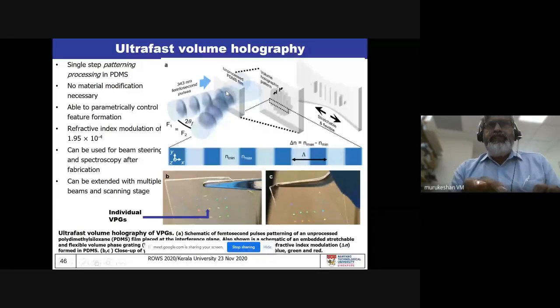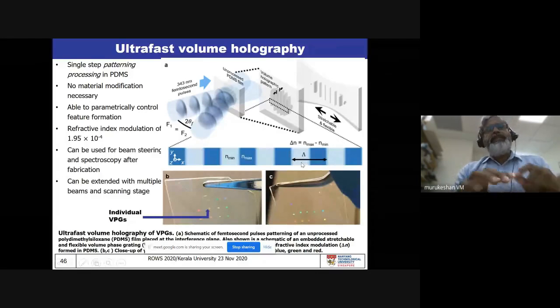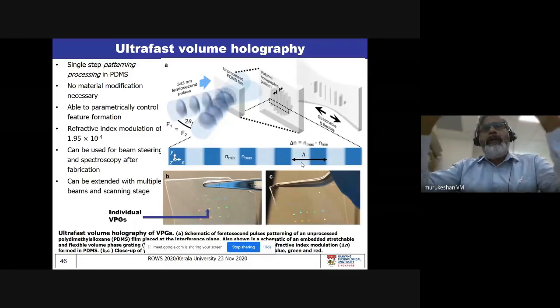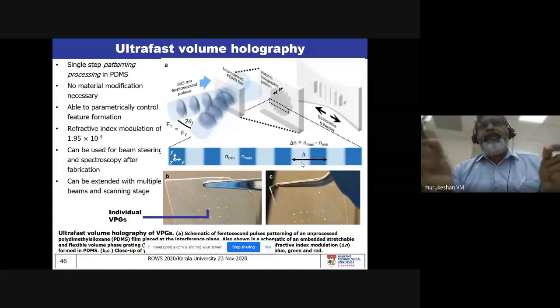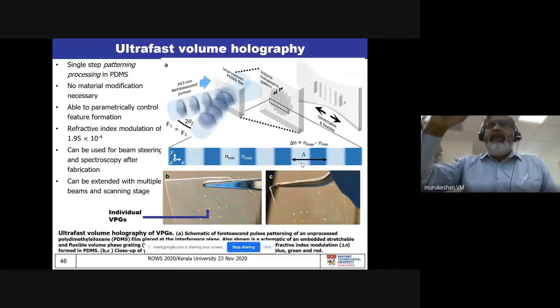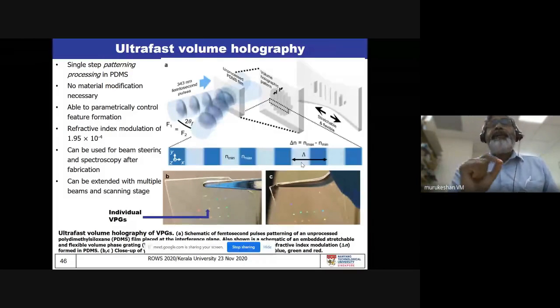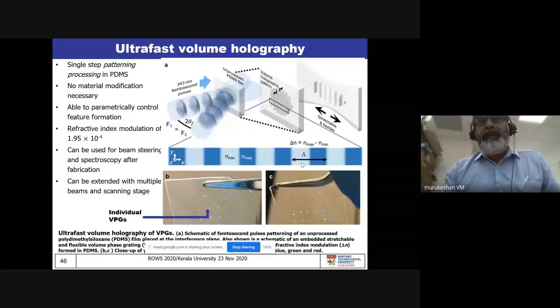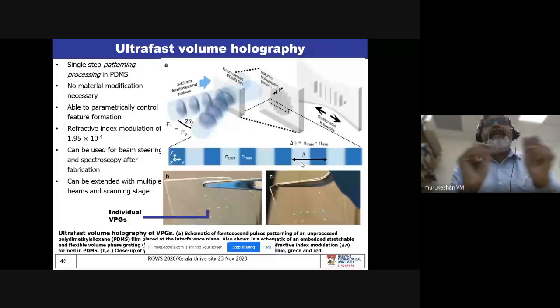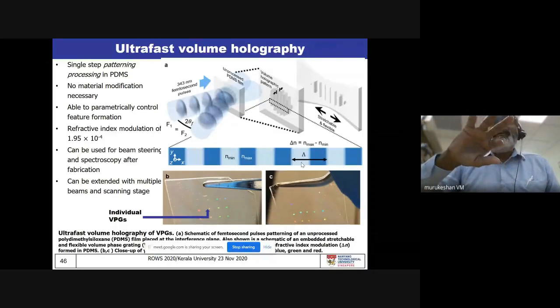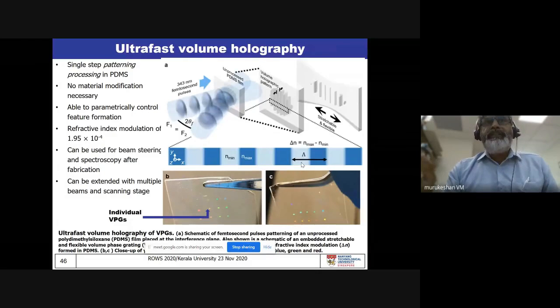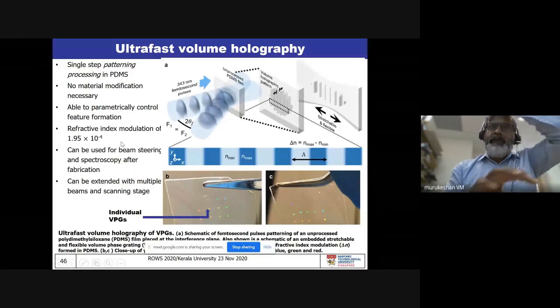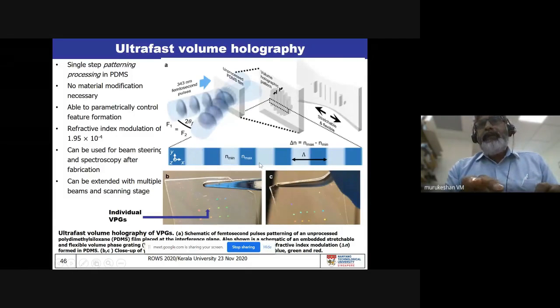And when you do this, you can actually modulate the refractive index. You might know that when you use a UV laser with a photosensitive optical fiber, you can inscribe gratings, such as uniform period gratings or chirped gratings or long period gratings like that for various sensing applications. This is something like that, but this is actually in the volume fashion, okay? The thickness is larger there, and you can see that the refractive index modulation here is 1.95 times 10 to the power of -4, of that order, and that is going to give you really a volume phase grating, not surface relief type gratings, okay?